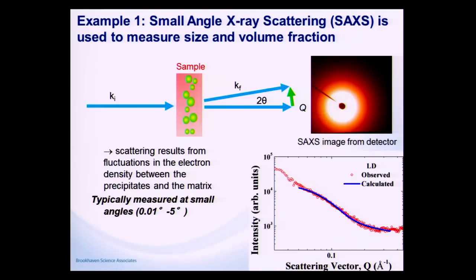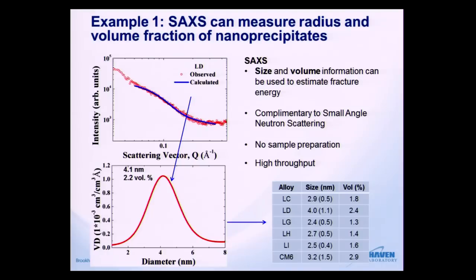Okay, now I'm going to switch to the next slide, but this image is going to be repeated. So here's the same image, and from this fit to the model, we're able to extract the volume fraction and the diameter of the nanoprecipitates in each of the samples. So now we have a list of our samples. In our case, we would have six samples. We also have the size and the volume fraction of the nanoprecipitates.